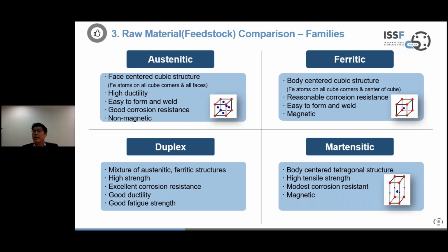All right. What about ferritics? It has a different structure. It is a body-centered cubic structure. In other words, the iron atoms are on all cube corners and the center of the cube. This gives it reasonable corrosion resistance, less than austenitic, but still reasonable. Easy to form and weld, and it is magnetic. Next, the duplex. It's a mixture of the austenitic and the ferritic structures. This gives it high strength, excellent corrosion resistance, good ductility, and good fatigue strength. And finally, we have the martensite material. It's a body-centered tetragonal structure, enabling high tensile strength, modest corrosion resistance, and it is magnetic.